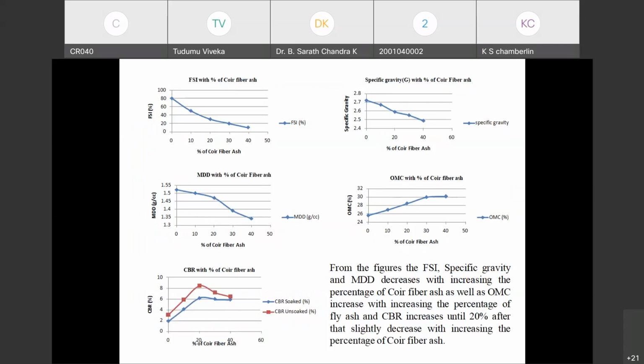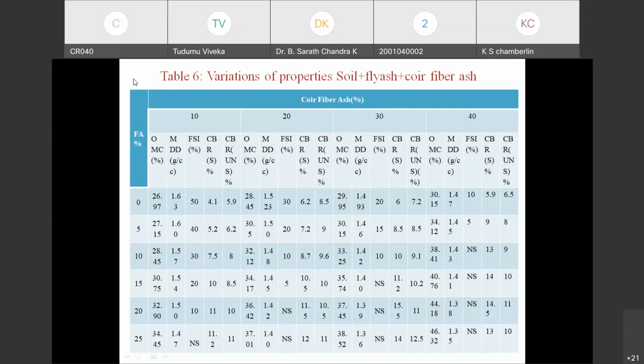From the slide, the FSI, specific gravity, and the maximum dry density decrease with increasing percentage of the coir fiber ash, as well as OMC increases, and CBR increases until 20%. After that it slightly decreases with increasing percentage of the coir fiber ash. And next one is this table shown as soil plus fly ash plus coir fiber ash with the percentages: fly ash like 0, 5, 10, 15, 20, 25, and the coir fiber ash 10, 20, 30, 40 percentages.